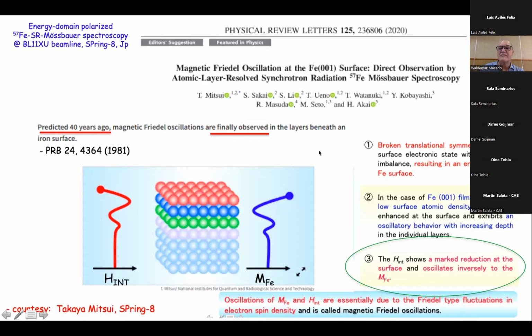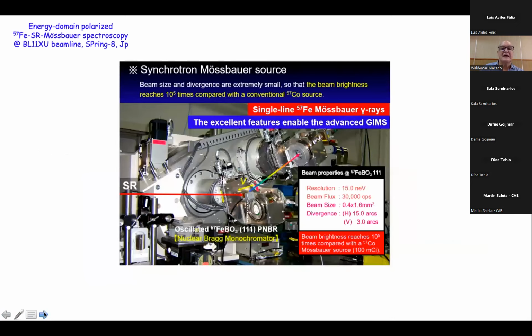and they have shown that because of the broken symmetry of the iron surface, we should observe an increase of the magnetic moment at the free surface of the iron, and a decrease of the hyperfine field of the iron atoms. What they did in these experiments is they used this synchrotron Mössbauer source, and you can get 10 to the 5 more counts, or more intensity, than a conventional 100 millicurie, very strong cobalt source for Mössbauer spectroscopy. That is what we use in our lab.